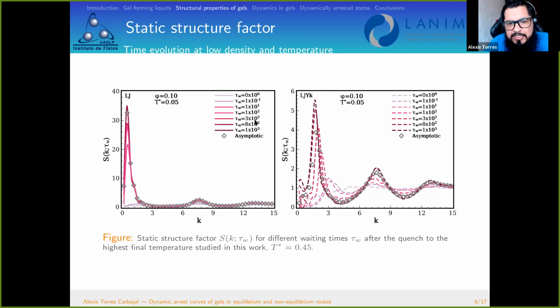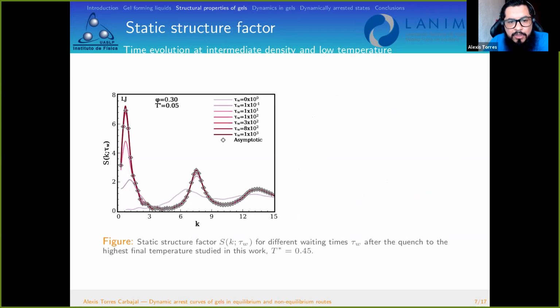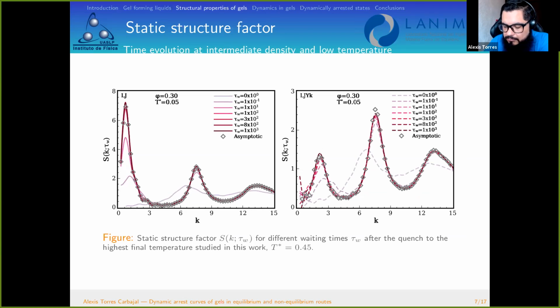We observe that both systems, the Lennard-Jones and the Lennard-Jones with Yukawa, exhibit the same features, but there is a subtle difference between them, because the first peak observed has different magnitudes in both fluids, even if the thermodynamic state is the same. I mean, the final temperature to which the system is cooled is the same, and the time observed is also the same. The final structures differ, although the qualitative behavior is the same. We also analyzed several thermodynamic conditions and observed a similar behavior.